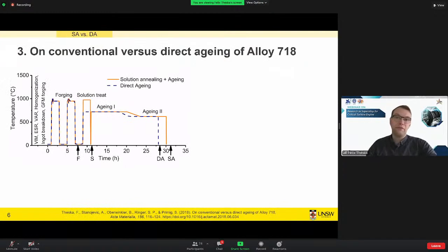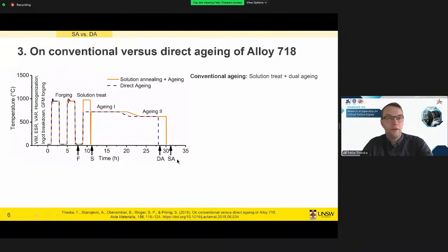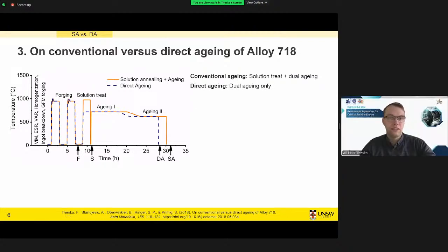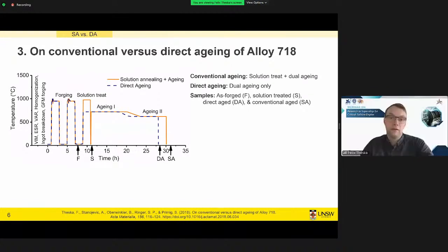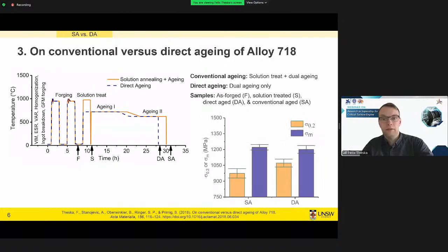All right, let's start with the first part of my research, which was a comparison of the conventional versus the direct aging of alloy 718. With conventional aging, I mean, after forging, the material is solution treated, followed by an aging process, which is usually done in this two-step aging. Whereas direct aging means we skip the solution treatment completely and the material is aged just after the forging. And if we want to study any differences in microstructure, we would start by comparing the as-forged condition, the solution treated condition, and then the final conditions, direct aged and conventionally aged.